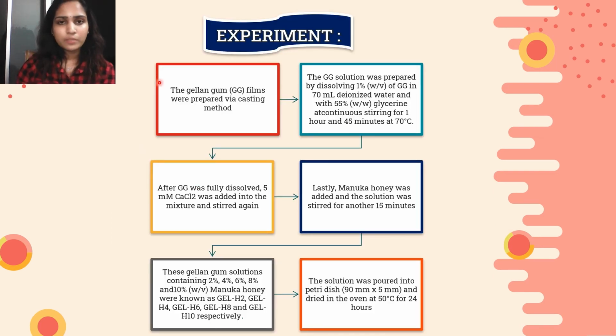The Gellan gum films were prepared via casting method. The first step is the Gellan gum solution was prepared by dissolving 1% of Gellan gum in 70 ml deionized water with 55% glycerin at continuous stirring for 1 hour and 45 minutes at 70 degrees Celsius, followed by, after the Gellan gum was fully dissolved, 5 mM of calcium chloride was added into the mixture and stirred again. Lastly, Manuka honey was added and the solution was stirred for another 15 minutes.